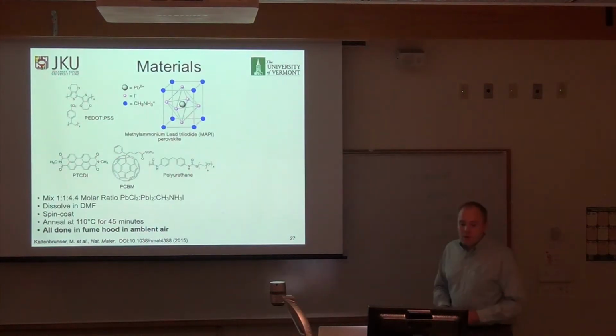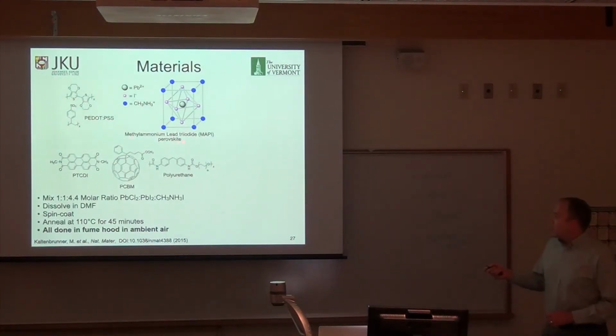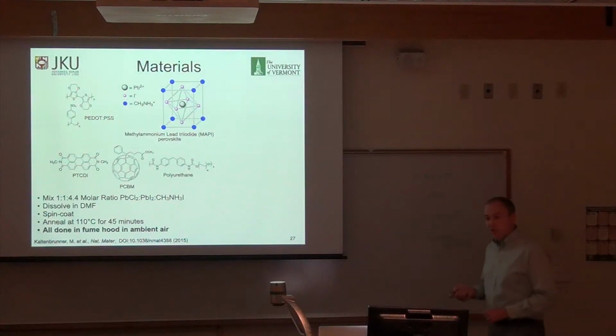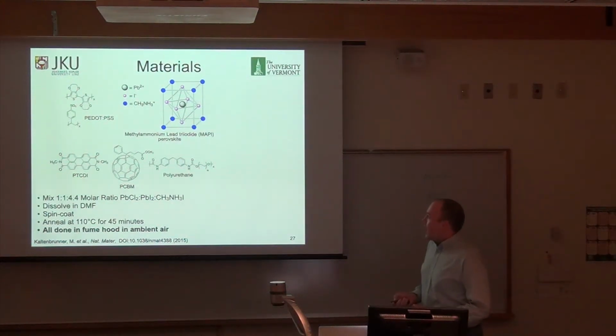The materials we use in our devices: this methylammonium lead triiodide perovskite. We process it from lead chloride, but as I said, there's no evidence that the chlorine stays in. We use this conducting polymer, PEDOT:PSS, as a selective hole contact and transparent electrode, and we use two other materials as selective electron contacts, and then polyurethane as an encapsulating layer. It's not a very good encapsulant, but it just prevents the devices from being scratched.